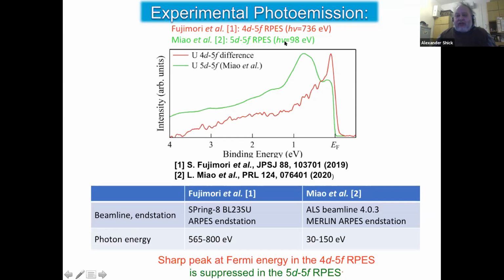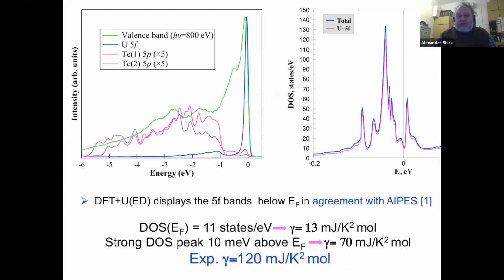Obviously, if you do these kind of experiments, you are surface sensitive because this photon energy is just too low to avoid the substantial surface contribution, while the other photoemission seems to be less surface sensitive. So if you do the comparison with the measurements of Fujimori, here is my density of states. Here, these are F states, and these are the P states. I just blow them up to be seen better. And this green line is the experimental data. Well, in fact, the comparison is rather good. So in a sense, our calculations support Fujimori's measurements and are in disagreement with Miao's measurements.